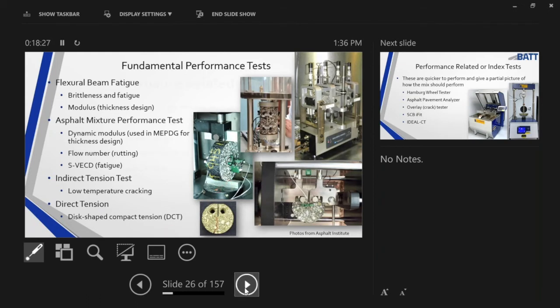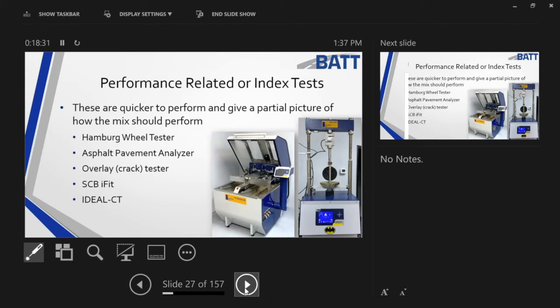When I began to look at what I call index tests, an index test is just that. It may not relate perfectly to rutting or perfectly to cracking, but it gives us an indicator of a go, no go. I can still get some relationship, and I know if I put more crush materials in, I see less rutting, but it's not as fine tuned. But these tests are perfect to help us move forward on a field level. And that's why we're trying to move forward with such as SCB, I-FIT, ideal CT, the overlay crack tester, APA, Hamburg wheel tester, and so on.